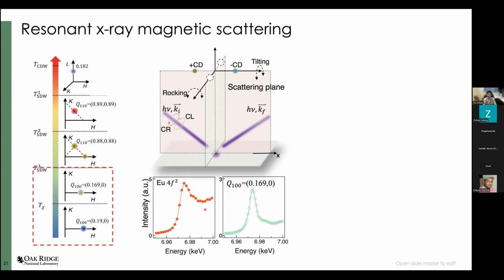So once you are on the resonant condition, your X-ray cross-section can be written in this form. The first term here is kind of an effective Thomson scattering cross-section. The second and third are related to the magnetic scattering. The third term is generally very, very weak. You can consider it as a higher order correction.